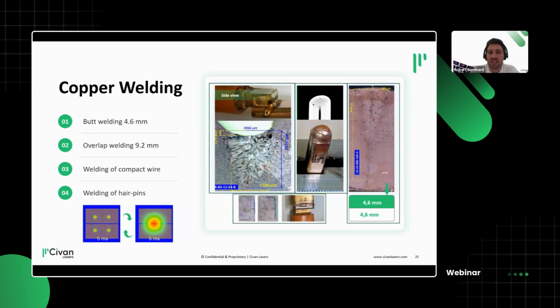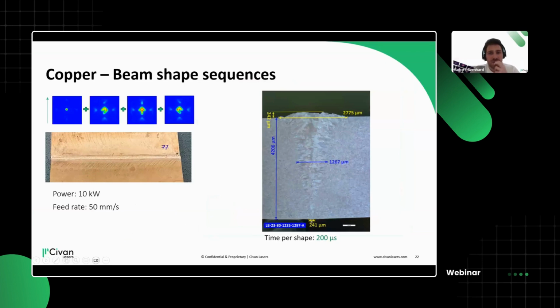And now by introducing dynamic sequencing, we can do fun things like melting the copper hairpin by placing 4 individual dots alongside, or even a line would be possible on each of these hairpins, and then switching to something more random. This means we have something steering and connecting them, so you get really this pearl being generated. We see also in copper, and I published this for the LANE conference just last year, that beam shaping allows you to get very good penetration, get rid of spatter, as well as making sure that the weld seam itself has the right dimensions.